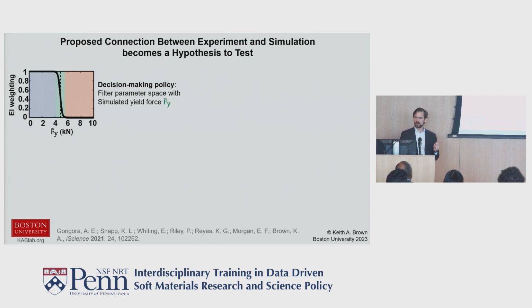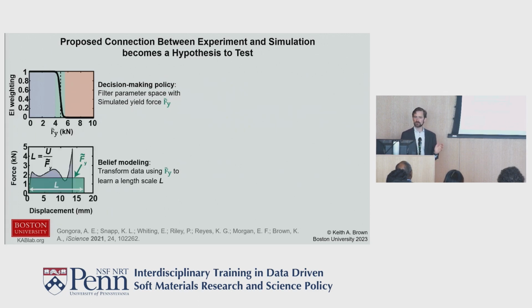So that's one. The second thing we did, I think, is conceptually much more interesting, which is to say that if you know anything about toughness, you probably know that it's kind of balancing 2 considerations. For something to be tough, it has to be strong, so it has to go high on a force displacement or stress strain curve, and it also has to be reasonably ductile. And those are generally competing ideas. The materials tend to only get one or the other. And so one thing we say is, well, we can predict the strength well enough from simulation. So what if we just try to learn how ductile the structures are?